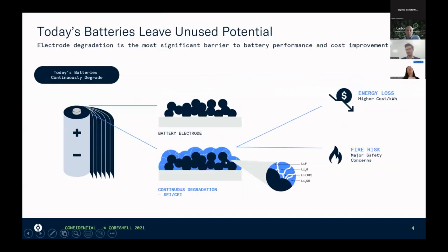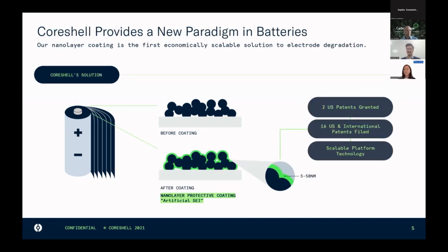So just jumping into exactly what we're focused on, which is solving surface level degradation on the surface of anodes and cathodes, really focusing on that formation of SEI or CEI that really can drive battery performance and lead to loss of capacity, but can also destabilize your battery for thermal runaway. And so the concept behind Coreshell's capabilities is fairly simple. Instead of allowing the surface of your anode or cathode to continuously degrade during cycling, we can coat the surface of your anode or cathode with a precise nanolayer film that still allows lithium to go through, but can prevent those side reactions from occurring.